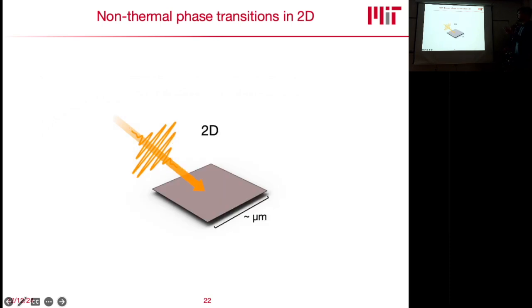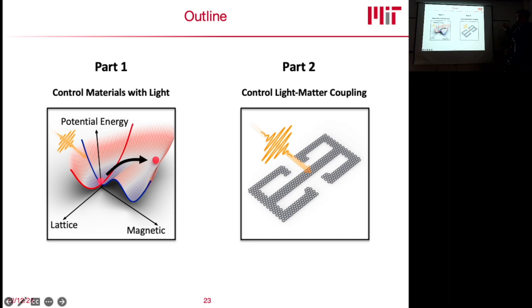So what people are now trying to do is engineer these phase transitions also in two-dimensional systems, where they use terahertz light to go to the two-dimensional limit and start probing similar dynamics. However, here we have a few roadblocks. Very low light-matter coupling, because now you're atomically thin along one direction. And usually these two-dimensional systems are very much confined to micrometer length scales, and at these length scales your light-matter coupling dramatically changes. Your terahertz couples differently to a macroscopic sample than it will couple to a microscopic sample. And this is exactly what I now want to talk about in part 2